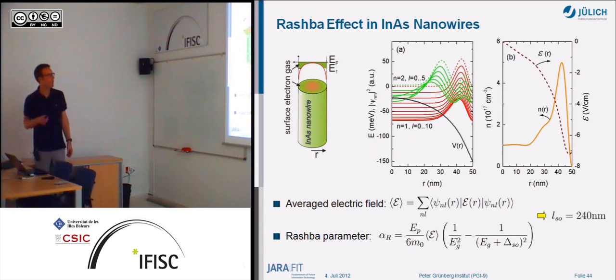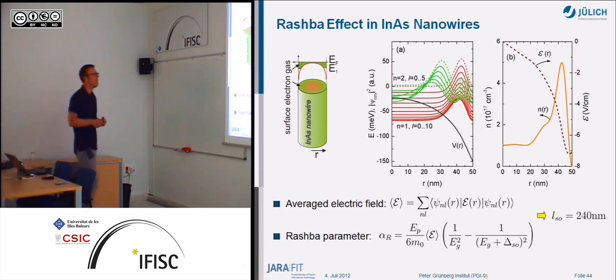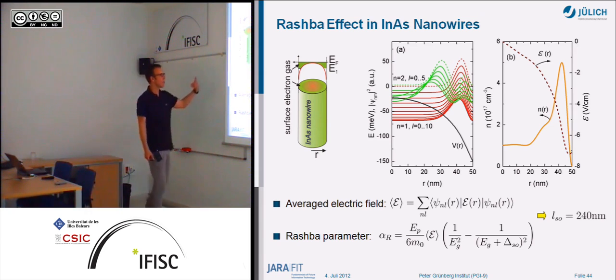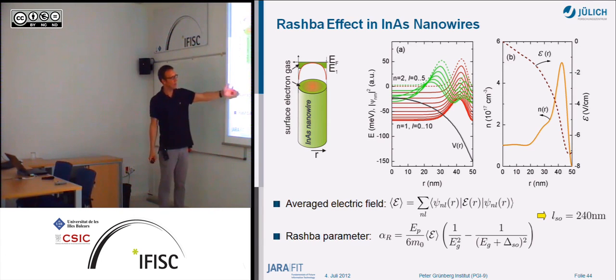You can do some calculation, in a similar manner as I showed before for the core-shell nanowires. This is the triangular potential here because of the surface accumulation. You have all these states here. You can calculate the average electric field, and then you can assess the Rashba parameter.